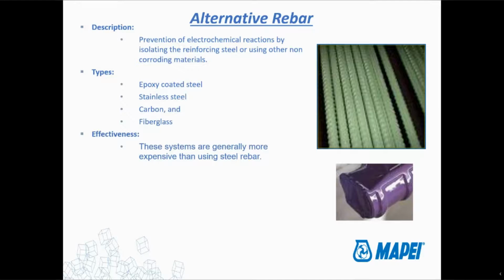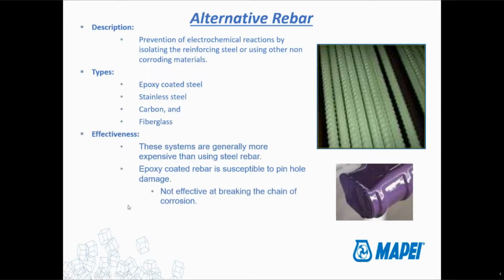With epoxy coated bars and stainless steel, I mentioned the issues with the epoxy coated bars. Stainless, it's more just slowing it down. So they're varying degrees of effectiveness. The epoxy coated bar, if it was done perfectly and it had no pinholes and no exposure whatsoever, it would certainly be very good.